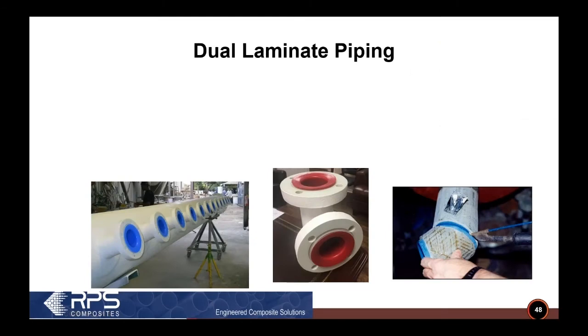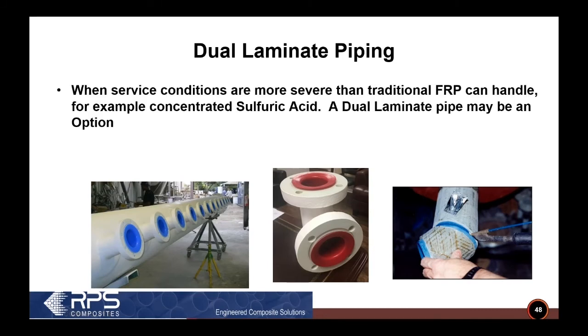Well, let me talk for a minute about something called dual laminate pipe, because that's a bit different than standard FRP pipe. So sometimes you get a severe service like sulfuric acid, concentrated sulfuric acid. If you go look in the corrosion guide that we have, you're going to find that straight FRP pipe is not recommended for concentrated sulfuric acid. However, what you can do is line the pipe with, for example, Teflon.